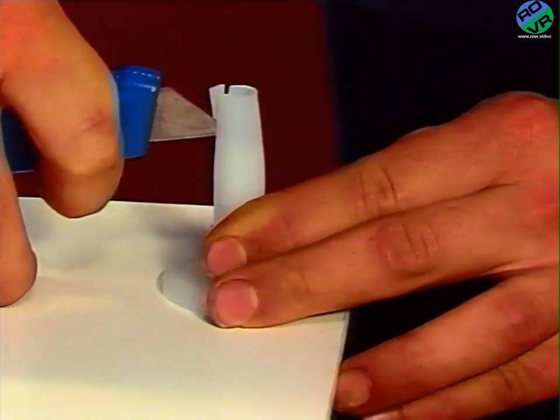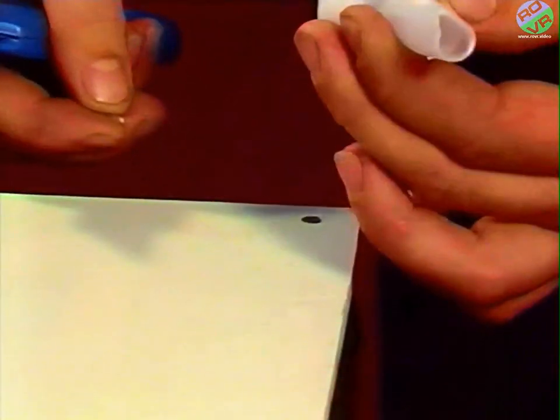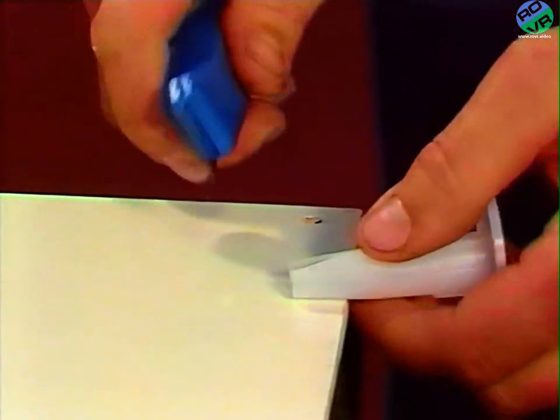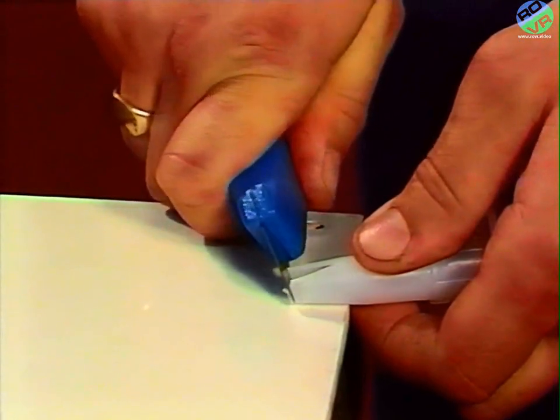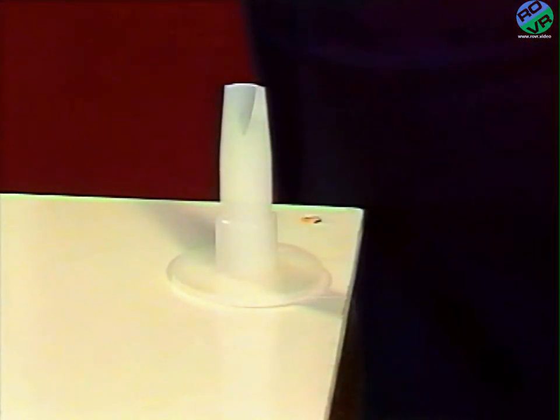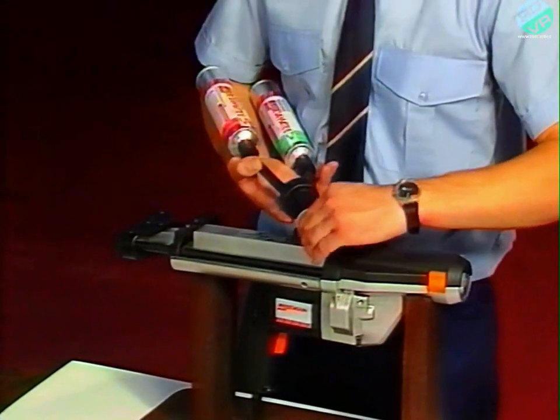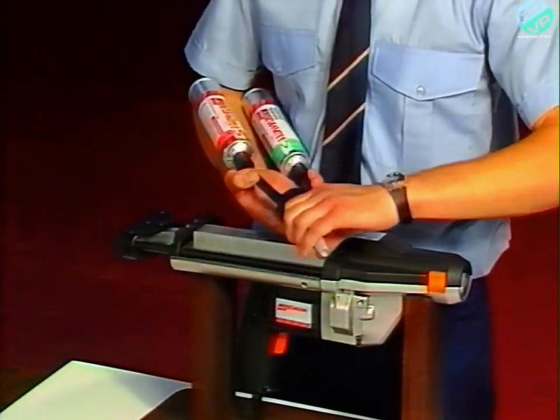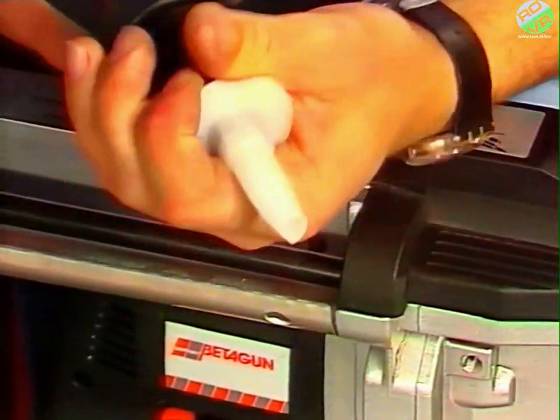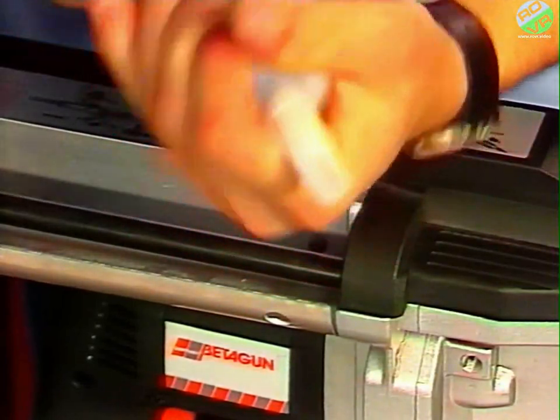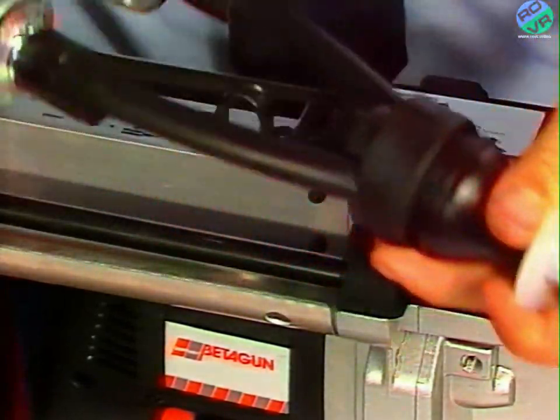Too narrow a cut is never a good idea, as it will make the bead too thin. A thin bead could lean over and possibly not make full contact with both body and glass. At the same time, too wide a cut will give too thick a bead and lead to a lot of messy cleaning up. The correct position for the nozzle is with the cut at 90 degrees to the line between the cartridges.